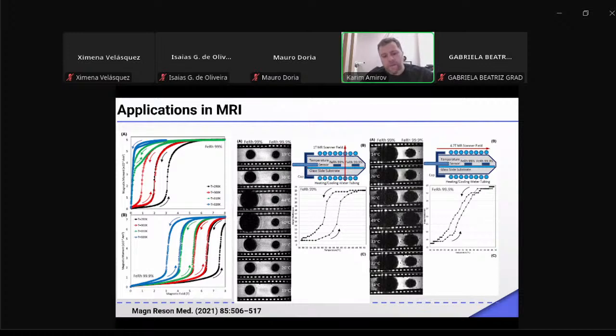You can see the reference to the work. And as you can see, the idea was followed. Iron rhodium has a sharp change of magnetization. It can be controlled by magnetic field and by temperature. It also depends on the composition of the material, and they put the iron rhodium material in a special insert in an MRI scanner field and detect its MRI signal. And in the antiferromagnetic state, it shows low signal.